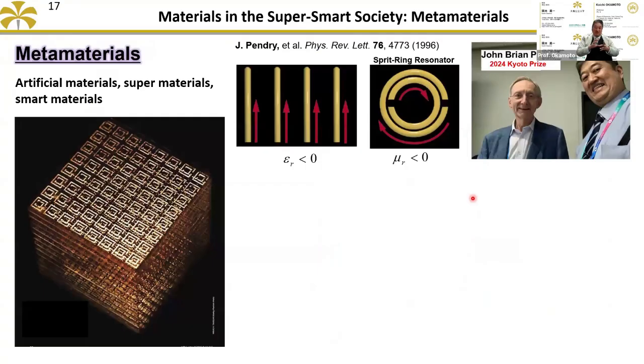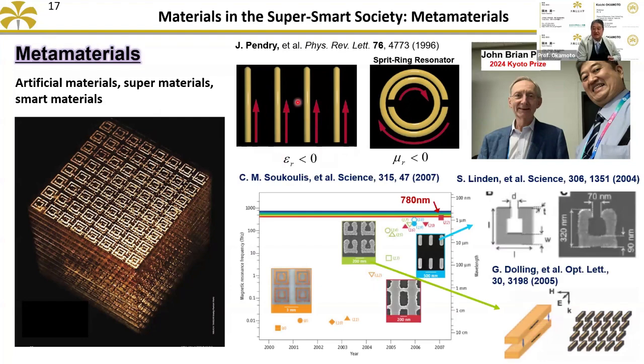Okay. Then for more flexible tuning, we want to use metamaterials. Based on nanophotonics and plasmonics, that's an artificial material based on nanostructure. That's called a metamaterial. John Pendry proposed and succeeded in fabricating that structure. The first time, he used a metal nanowire structure and a split ring resonator structure. By combining these structures, he can achieve negative permittivity and negative permeability. So if both values are negative, the refractive index becomes negative. So a negative refractive index is available. Then he succeeded experimentally in the microwave region.